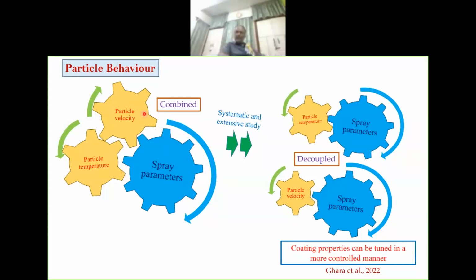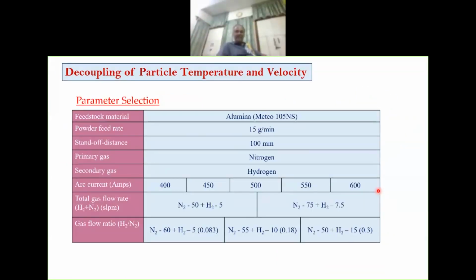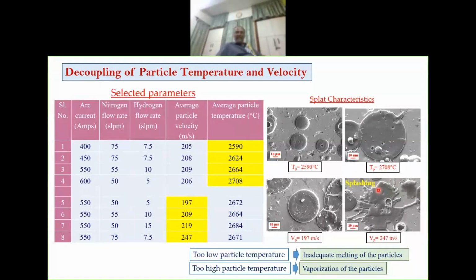Is it possible to decouple them? As said, in the laboratory scale, yes. And it was done in 2022 for the first time to our knowledge. What we achieved here is like this. We cannot keep the velocity exactly constant, but if we confine it to a very narrow range, the temperature could be varied. We have taken an alumina particle and melting temperature is around 2200. Keeping close to it doesn't help because in most cases the particle will be unmelted. So you superheat the particles a little bit. Similarly, we kept temperature nearly constant, not exactly constant, and we could vary the velocity.